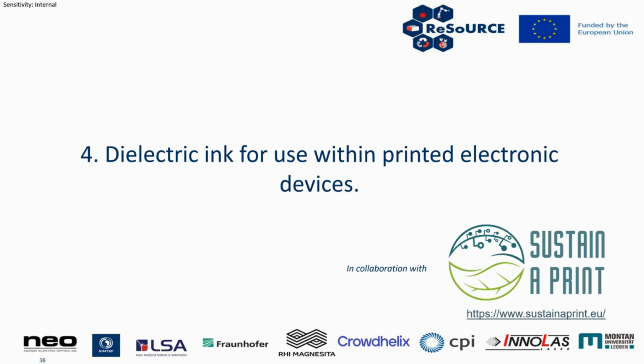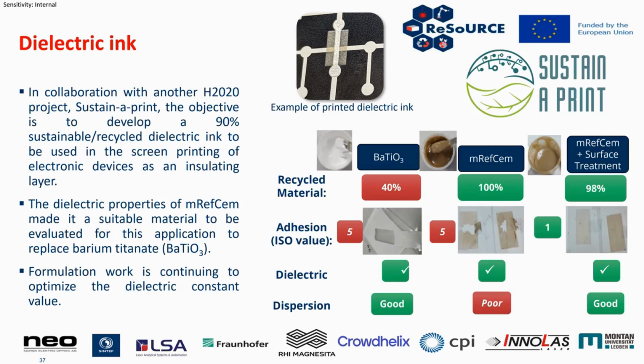Another application that we were looking at was the use of dielectric ink within printed electronic devices. These are cheap electronic devices that are mass market; they're not high value in and of themselves. This was in collaboration with another Horizon 2020 project, Sustainaprint. We have the link to their website there if you want to have a look at that. What we're doing is looking to replace the dielectric ink in an electronic device. This is an ink that you use to coat over an electronic track, so you can then print over the top and you don't get interference between the 2 tracks themselves. An example of that is the top middle there. So we were looking at whether we could replace the barium titanate with our material, in this case the mRefCem, because that was the most dielectric of the 2 materials.